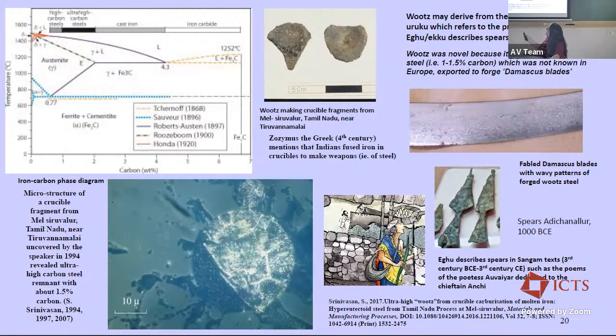And these are typically the remnants from some of these crucibles which I had uncovered at a site called Melsiruvalur. And you see here that the composition is very typical of what we call ultra high carbon steel, of about 1.5% carbon, where you have the pearlite network forming within this honeycomb network with prior austenite going all around. And this structure can only form if the steel has actually solidified from the point where austenite had formed. Otherwise, you wouldn't find this honeycomb being formed. So that means it has reached very high temperatures.